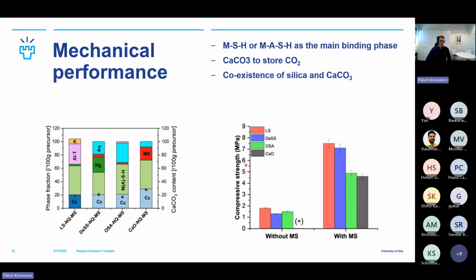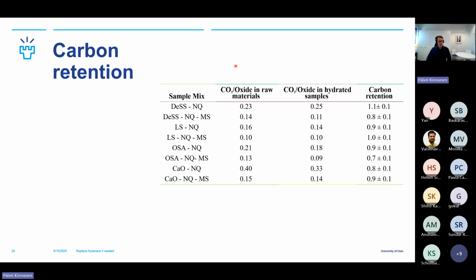So we could see that we have coexistence of silica and calcium carbonate, and the calcite does store the CO2, and the MSH gives a binding phase to the bricks or to the precast elements. And in terms of the carbon retention, we calculated how much of the CO2 actually stays in the brick and how much is leaked out. We can see that 70 to 100% of the CO2 is retained in the material. And this is, of course, really good news.